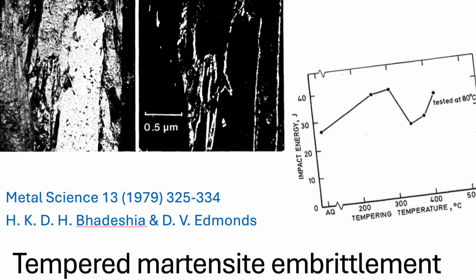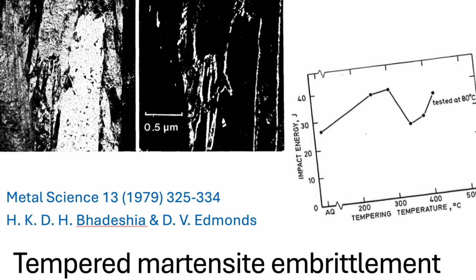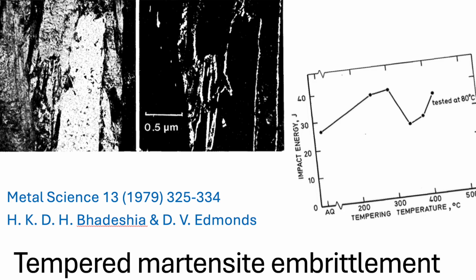We should probably pause there because this sounds like the core of the failure mechanism. Cementite is naturally brittle, we know that. But why is it so destructive here, sitting as a film between the laths? Is it the amount or the shape and location? It's primarily the location and the morphology, the shape. You see, if cementite forms as, say, rounded globules dispersed within the steel, the material can sometimes absorb energy by deforming around them. Okay, it can kind of flow around it? To some extent, yes.